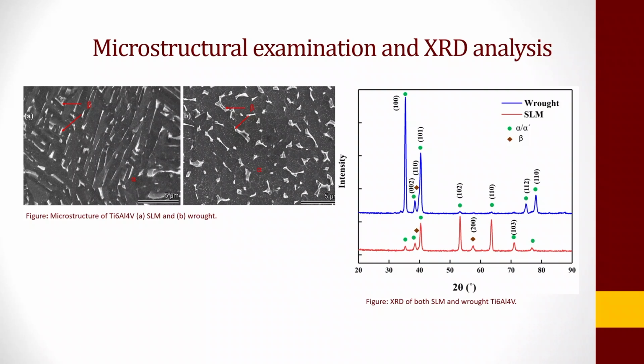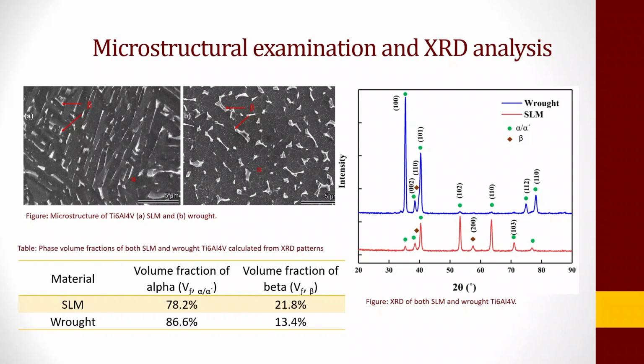So this was the basic difference in the microstructural analysis. And then when we did the XRD analysis, we did not find any significant difference, except that we did observe a few extra peaks, mainly at 2 planes I would like to mention, the 102 and 110 planes. We did see strong peaks at those planes in the SLM sample. And by the way, in the XRD patterns, we did see that the volume fraction of alpha prime is a little bit higher for wrought as compared to SLM.